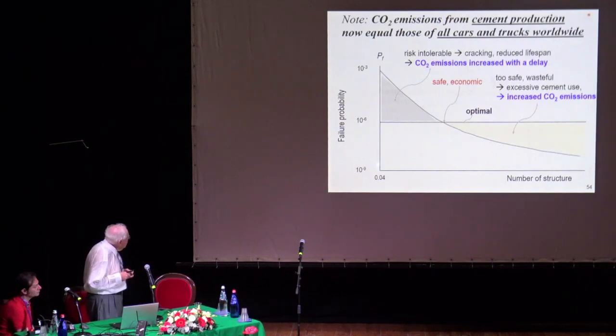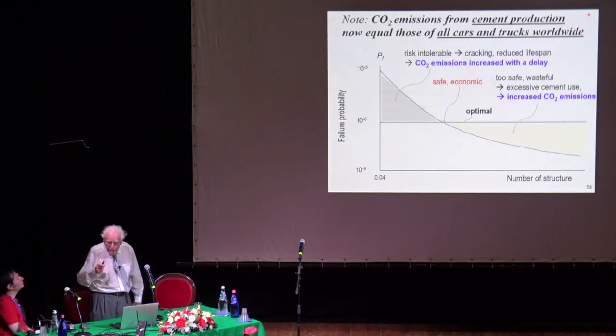Anyway, I put here failure probability of various structures, assuming they are organized by the value of failure probability. This is the number of structures, 1, 10, 100,000, and so forth. So this is a decreasing curve. If you have more structures, you can find failure probability. Optimally, you have 10 power minus 6. Some structures are over-designed. They are too safe, wasteful, which leads to excessive cement use, and that significantly increases CO2 emissions. So good safety factors means lower CO2 emissions. We are wasting concrete, which has terrible effects on the climate.